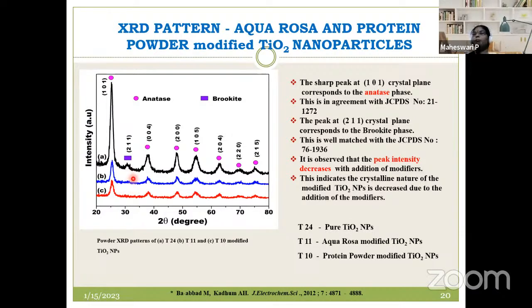There is no peak shift which we have observed here, because whatever material we have added here is not changing the total lattice. They are just modifying only the surface. That is the reason you can observe the intensity alone is decreasing with respect to addition of modifiers, and there is no peak shift that is obtained over here.